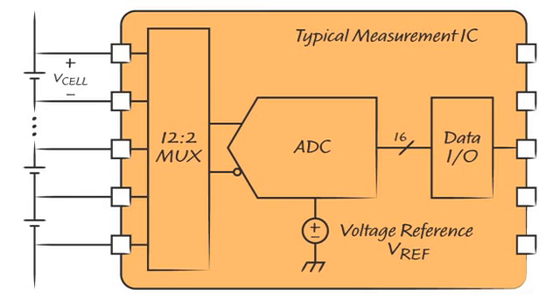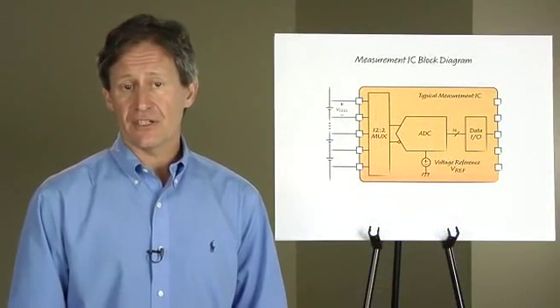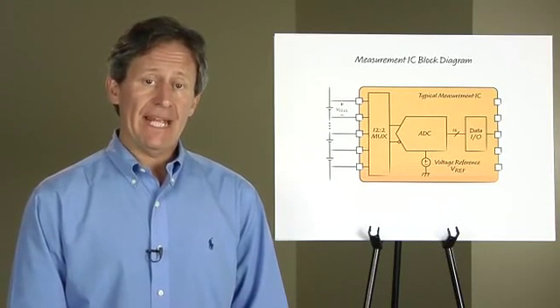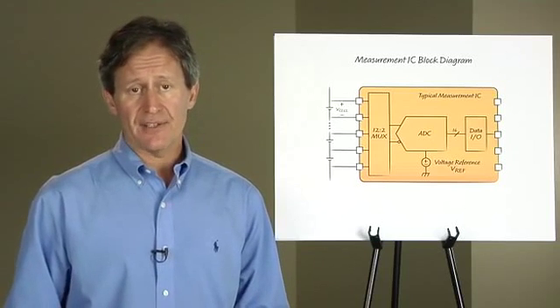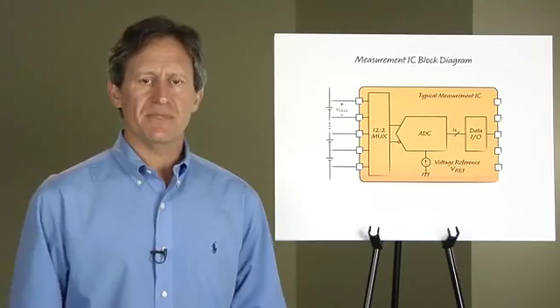For example, circuit board assembly can really affect voltage references. The ICs are subjected to 3 thermal shocks from the soldering process. The silicon experiences mechanical stress from the expansion and contraction of the plastic package and the copper lead frame. A band gap reference behaves like a strain gauge, converting the mechanical stress into voltage changes. A zener reference is almost immune to mechanical stress.